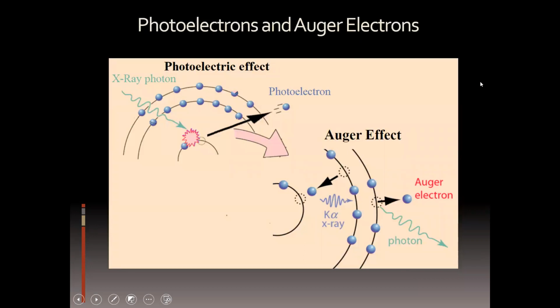There. So there are two different types of effects that take place when you irradiate with X-rays. One is the immediate emission of a photoelectron, like that. X-ray comes and gives it energy, and out it comes. This would be the photoelectric effect. This is the XPS part. But there's also another way. This hole can be occupied by another electron that jumps down, and in doing so, it will lose energy. The energy can be taken by another electron that comes out. This is known as internal conversion, and you end up having the second electron coming out through what is known as an Auger process. It's an Auger electron.